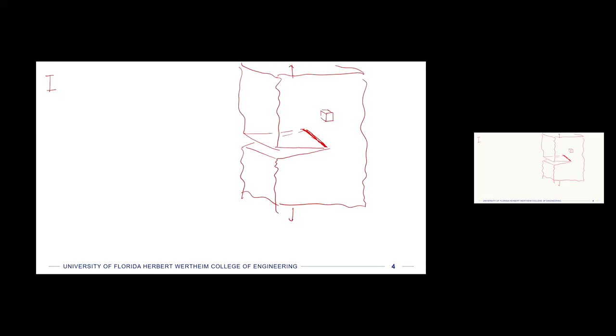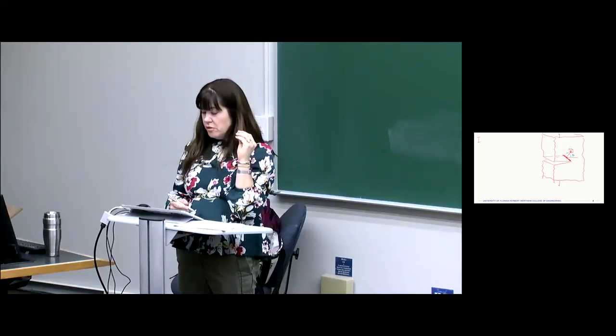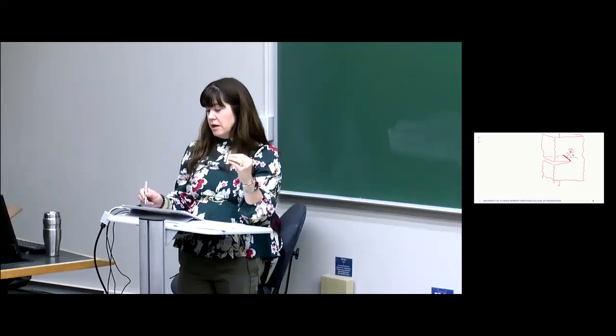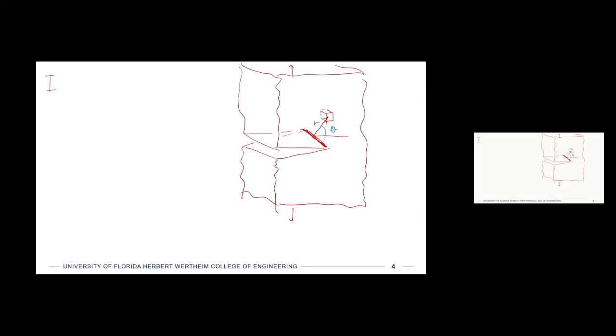And so we will have some things that we care about, like how far is that from the edge of the crack? We're going to call that little r, right? That's a radius. That's how far away it is. And then we'll also define an angle, which I drew the r right where the angle needs to be. So this will be r, and this will be some angle theta. And then we'll think about the stresses at that little element. And you will probably start to think, okay, if r goes to 0 and that element is on the crack tip, my stresses are going to go to infinity because it's kind of like a discontinuity in the material, right? It's no longer a continuum. All of our equations break down. So that's one thing that we'll come up with in these equations, is that if r goes to 0, stress goes to infinity.